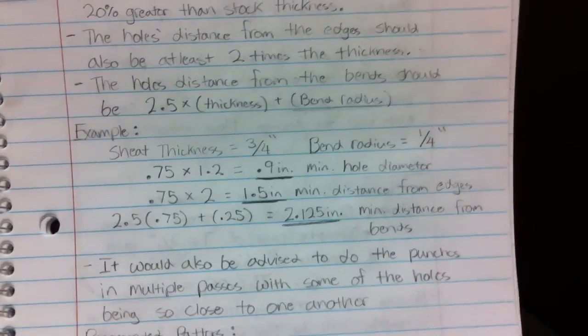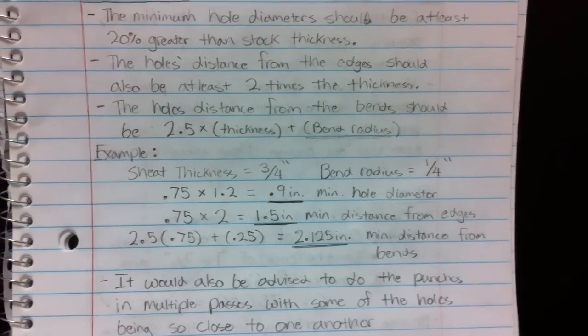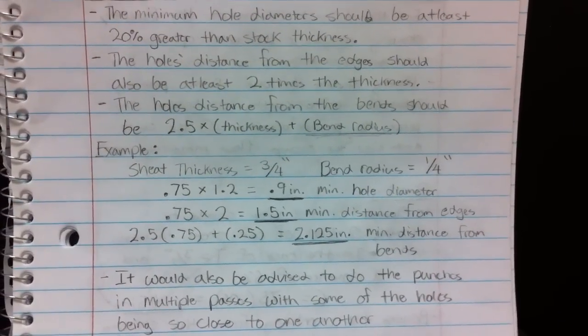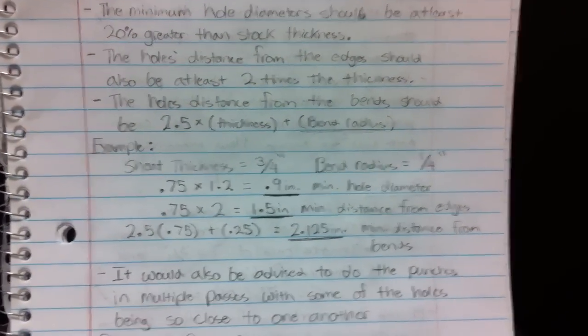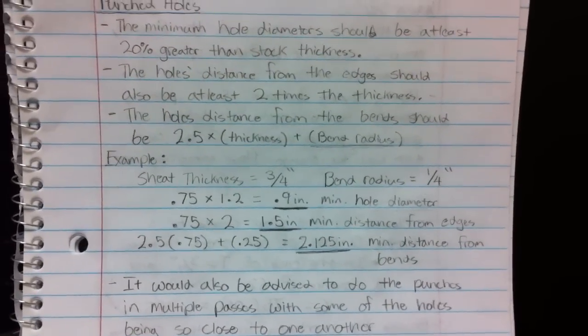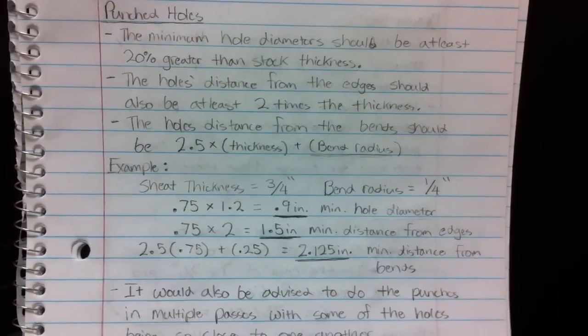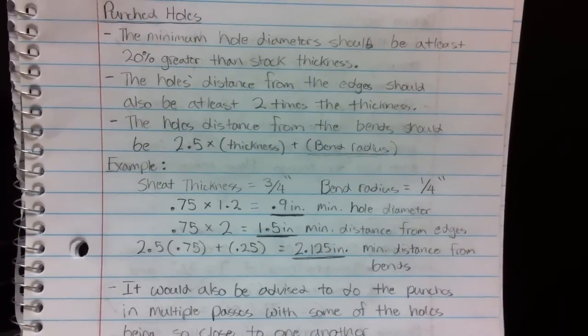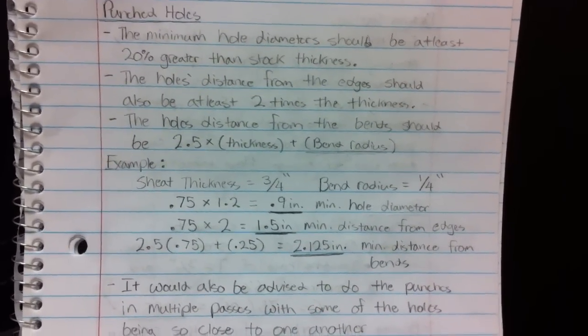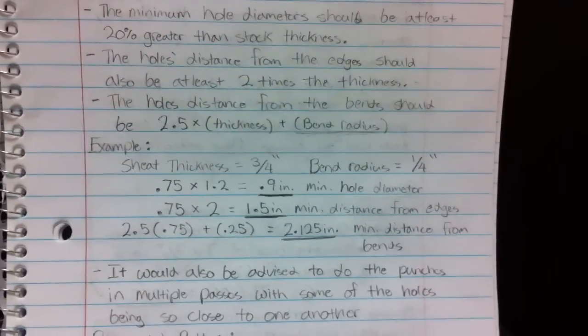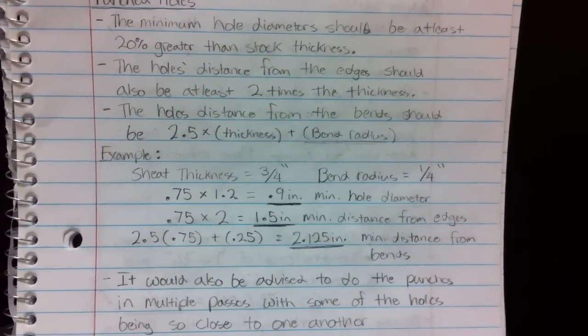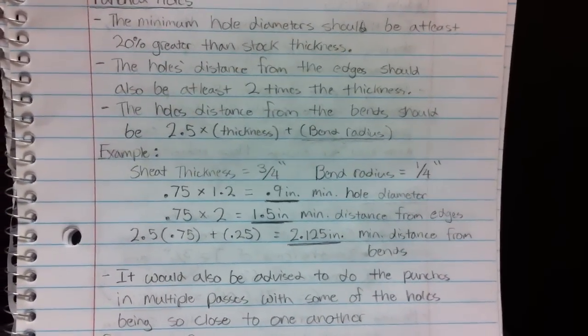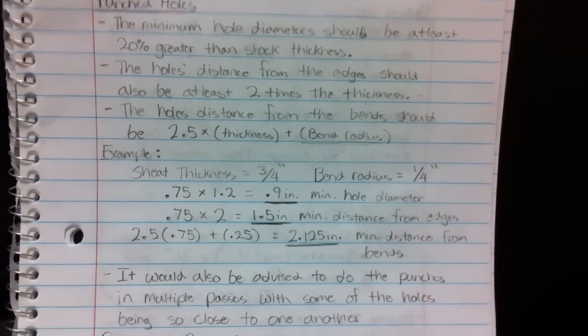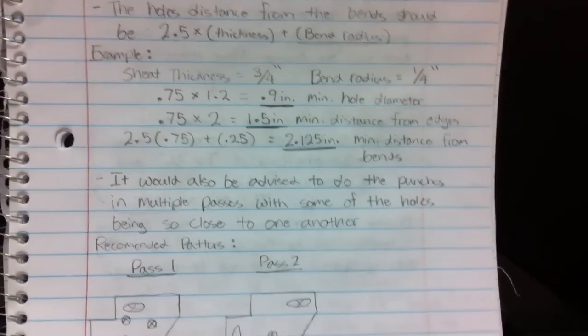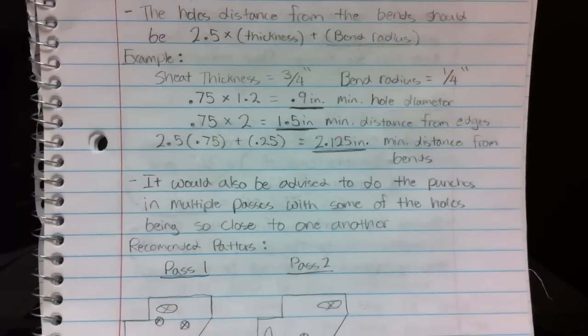Say our stock thickness is 3/4 of an inch, and we have a bend radius of 1/4 inch. Our hole diameter would then be 0.75 times 120%, which would be 0.9 inches, and then 0.75 times 2 would be 1.5 inches, and that would be the minimum distance from the edges. And then for distance from the bends, we'd have 2.5 times 0.75 plus the bend radius of 1/4 inch. That would be 2.125 inches, and that's the minimum distance from the bends.